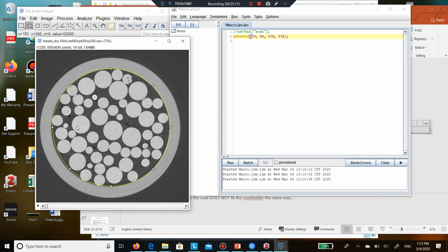Because the way you record or assemble is not perfect. And often when you put things in, it happens downstairs in the medical CT a lot. Things are hanging, so slightly shifted. We're talking about a few millimeters over this, but you see it in images. It's annoying as hell in images, but it's what it is. And if you are then processing this data, that can introduce, of course, error in the calculation of porosity and everything else.